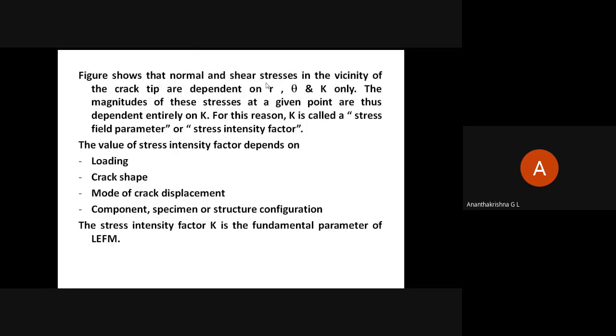The normal and shear stresses in the vicinity of the crack tip are dependent on r, theta and K, right? The magnitudes of these stresses at a given point are thus dependent entirely on K, the stress intensity factor or stress field parameter. The stress intensity factor depends upon loading, crack shape, mode of crack displacement, whether it's mode 1, mode 2, mode 3, though the discussion is all about mode 1 only, and component or specimen configuration. This is the fundamental parameter of linear elastic fracture mechanics.